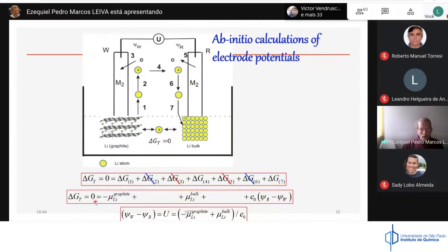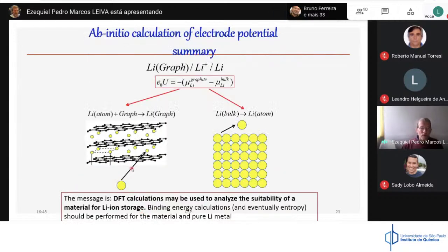You can see that the potential difference of this cell is nothing but the difference of 2 chemical potentials. That means that if you take the chemical potential, in this case of lithium in graphite, and you subtract the chemical potential of lithium in the bulk and divide by the electron charge, you get the potential of the cell. That's why you can, in this case, calculate. That means that you can very, very easily calculate the electrode potential by ab initio calculation.